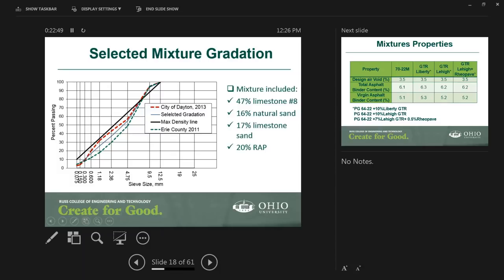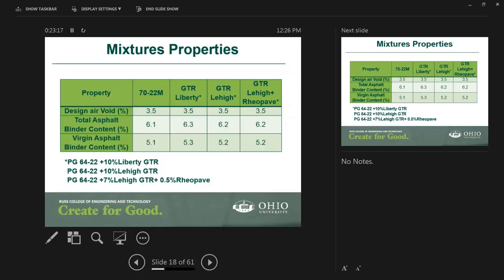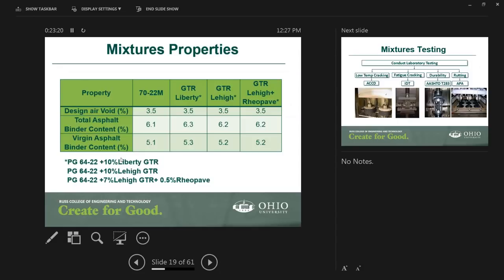And what we did is we selected a gradation that is between the ranges that we have for all the asphalt mixture gradations that were obtained, basically used in Ohio. In that gradation, we included the aggregates that you have seen here, limestone, plus, very important, we used 20% RAP in that asphalt mixture. One of the reasons we wanted to use that high RAP is that certain cities are actually allowing up to 20% RAP in an asphalt mixture. So we wanted to go to that high end.